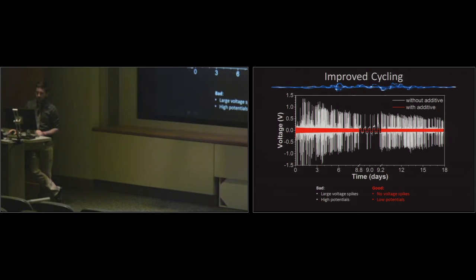If we look at the zoomed in portion here, you can see that it's nice and flat. There's no voltage spikes during the entire 18-day test period. It's nice, flat, smooth. This is about as close to ideal as we can get with this system.